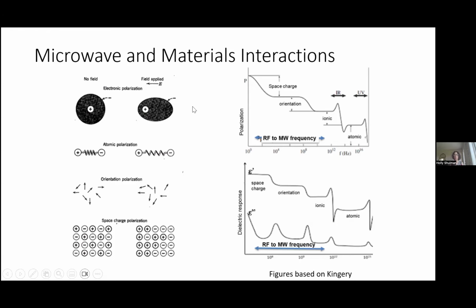So something like electronic polarization happens at such high frequency, we never have to worry about losing that if we go to high frequencies. But in this frequency range, we have quite a bit of orientation polarization and space charge polarization. So you can see that here. And this polarization drops off, space charge goes out first, orientation polarization drops off as you go to higher frequencies. This is because those mechanisms of polarization can't follow the field. So it's like the field is flipping back and forth, and certain polarization mechanisms can always keep up, like electronic, and others start to be frozen. Once the field switches the other way, they can't move at all.